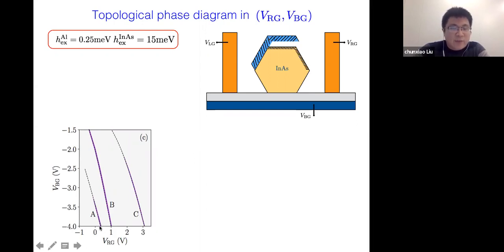Now we can see that the topological lobes are in the diagonal direction in this phase diagram. And actually these dashed lines are equal chemical potential lines. The chemical potential is 0 along these dashed lines, because when you make the back gate more negative, you increase the energy of your subband mode. And at the same time, if you increase the right gate voltage to a more positive value, you're actually lowering the energy of your subband mode. So along these dashed lines, the increase and the decrease of the energy is compensated by these 2 gates, so it keeps 0.